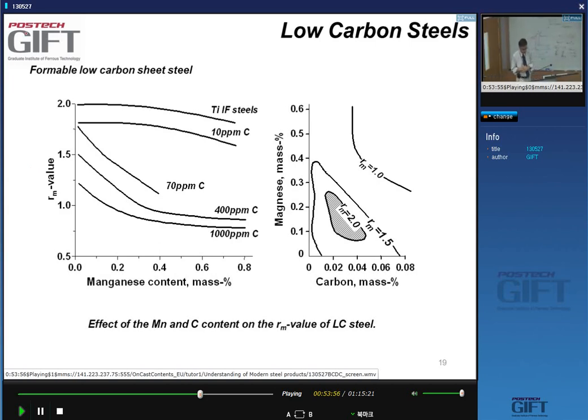So what we see, when we look at the R value, and we have 1,000 ppm of carbon, then this is our R value here. If we have 400 ppm of carbon, our R value increases, and we're here. If we have less than 100 ppm of carbon, 70 here, 10 ppm here, we see the R value increasing and increasing, yes? If we have an IF steel, a titanium IF steel, there's no solute carbon, so the carbon is present as titanium carbide, and our R value is even higher, you can see. So low carbon is very good.